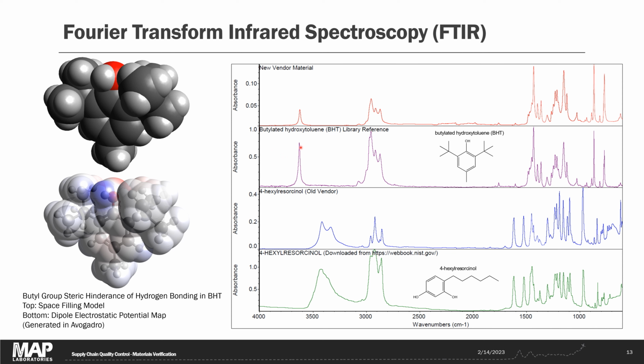The reason that this OH stretch is so narrow in BHT is that this OH group is kind of trapped in there between these butyl groups. So just physically, it's difficult for this molecule to align to itself correctly for hydrogen bonding. It's just a really interesting physical aspect of the molecule manifesting in the FTIR spectrum.